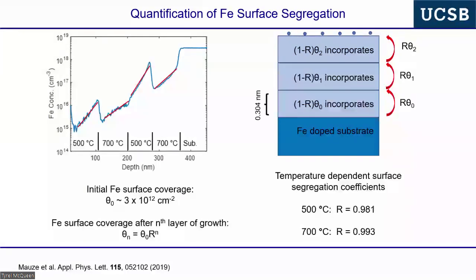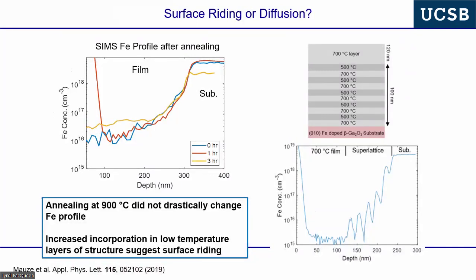And you do this far from the active region in the growth, in epitaxial growth, and it's really impurity capture. This superlattice that we developed here is an impurity capture superlattice because we can go from very high impurity concentrations down to very low impurity concentrations and completely consume all of the junk on the growth surface. And we're probably consuming a lot of other stuff, but we don't know what to look for in the SIMS depth profiles. Okay, so it's not bulk diffusion. The whole literature always talks about the iron diffusion tail. It's not bulk diffusion. It's surface segregation with weak incorporation.